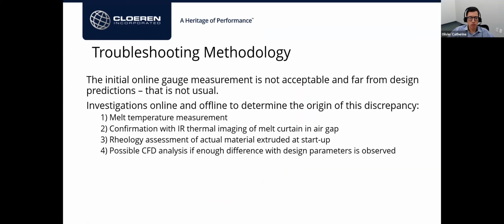So what did we do from there? Well, we suspected that the material melt temperature was not what they were specifying. So we used 2 techniques to characterize that. One is to measure the melt temperature in the flow itself, and also to measure the melt temperature in the air gap, the material coming out of the die, with IR imaging. And finally, we wanted to make sure that the material that they were actually extruding that day was the same as the one that we designed the die for.